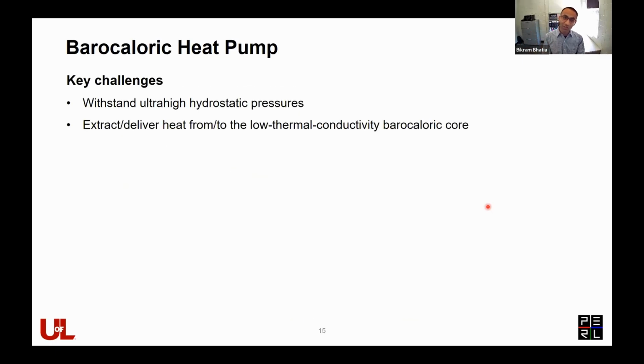performance. And so the next step was to build the device, which is what we focused on, which hasn't been done except for one work which did not report the experimental performance for some reason. But we wanted to do that. And the reason we think this hasn't been done so far is primarily two reasons. One is we are applying really large pressures for these barocaloric devices, on the order of about 400, 500 megapascals of pressure. That's 2 orders of magnitude higher than what you typically have in a vapor compression system. So designing something that can withstand that high pressure is critical and it's not trivial.